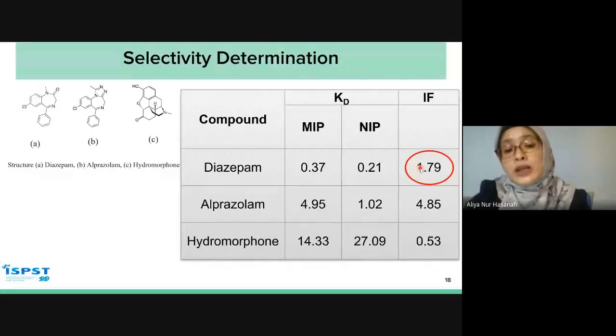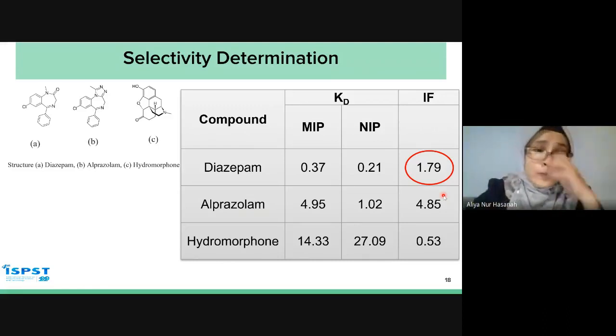But when we compare the result with alprazolam, which has a similar structure to diazepam, we see that alprazolam has a larger imprinting factor. After we analyzed, we can see that the 3D structure of alprazolam is smaller. So there's also physical adsorption in the pore, which makes alprazolam have the higher imprinting factor.